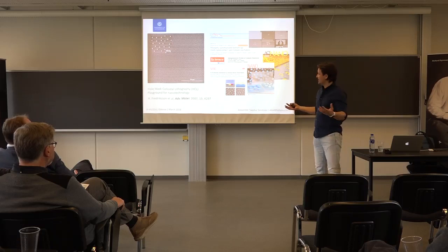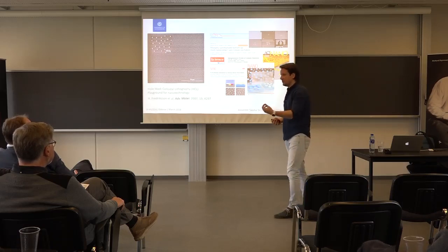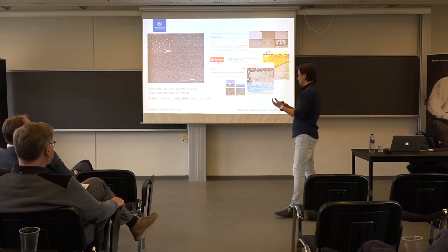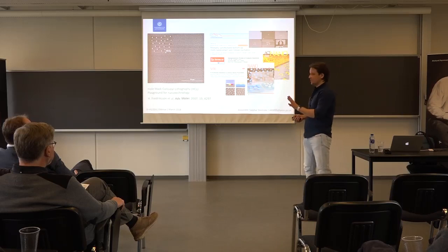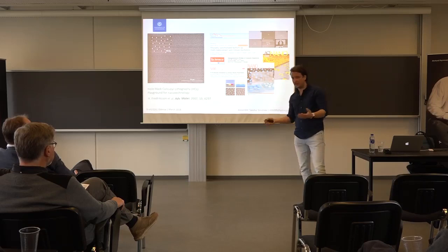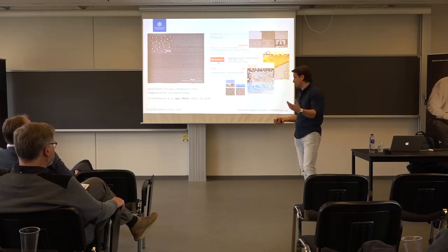with different configurations of your nanostructures of different materials. So it's a really easy and cheap method of either making your functional nanostructures directly or just testing things. Essentially, you don't even need the clean room for that, because it's really a wet bench process. You have aqueous solutions of the colloidal particles, and you need some instruments to deposit metals, of course, or to spin coat the resist, things like this.